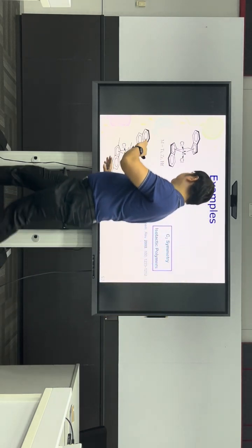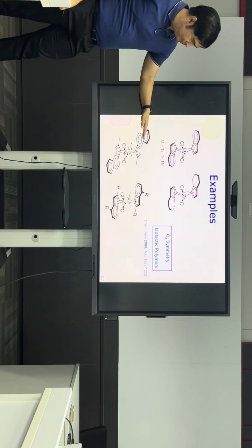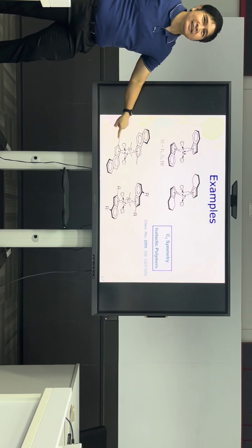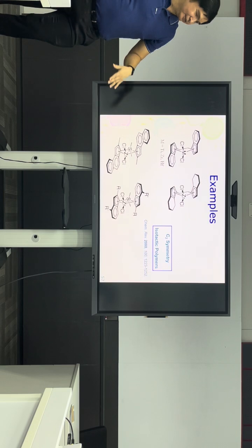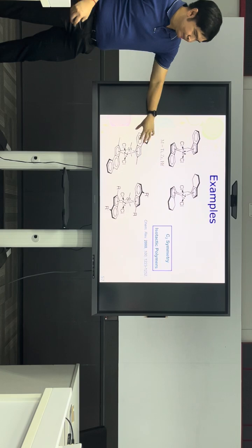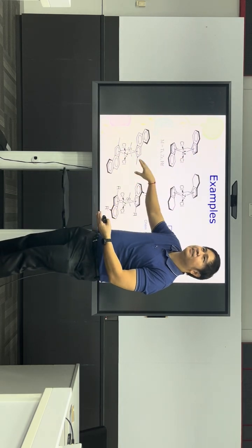Or even this one, you approach from this side. Well, it's tough to say. I don't know which one is larger between methyl or the aromatic here. The reason I'm not sure is that methyl occupies larger space in 3D, but this is planar. Even though it looks large, it's planar. So I'm not sure which one is better, but let's assume this is larger. That means right hand side is good, right? When you move to this side, it's the same way. Right hand side is good. So yes, you can get the isotactic polymer.